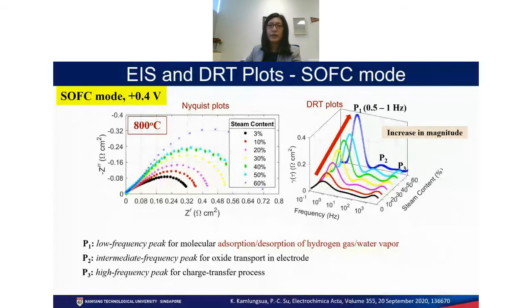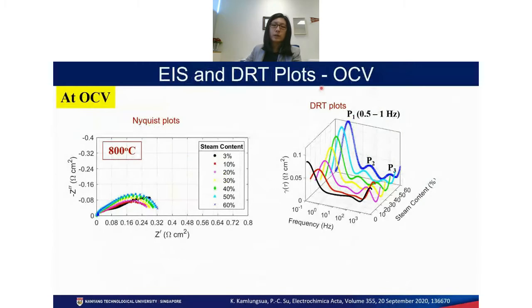Now let's look at the OCV. This is the OCV EIS and DRT plot. We can see that again 3% is the lowest and it increases all the way to 60%. The impedance is rather stable with all moisture contents. And we look at the DRT plot. For the first peak, when it's black, which is the lowest moisture content, it is a bit higher. Then when it goes to the red, which is 10%, a slight increase of moisture contents, it dropped. And then it starts to increase again. So it goes through a drop in peak one and then increases.